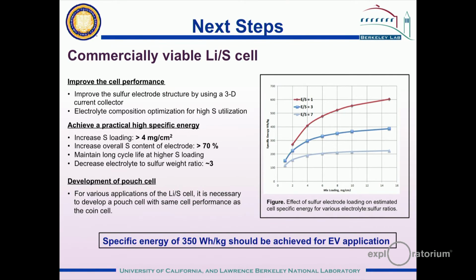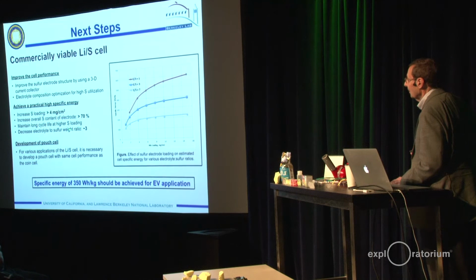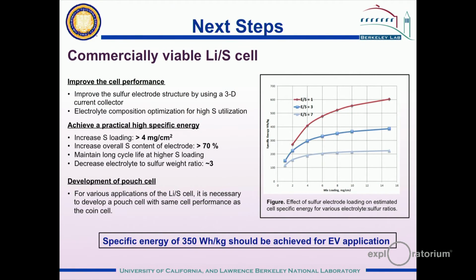As we put more and more sulfur into the positive electrode, it takes a longer and longer time to discharge and recharge the cell. So it's going to take us quite a few months to really test the cycle life of our high loading cells. The electrolyte in the cell is just dead weight. It does not contribute any of the energy that is stored in the cell. So we want to minimize the weight of electrolyte in the cell, and we would like to have less than 3 times the weight of electrolyte as compared to the weight of the sulfur in the cell.